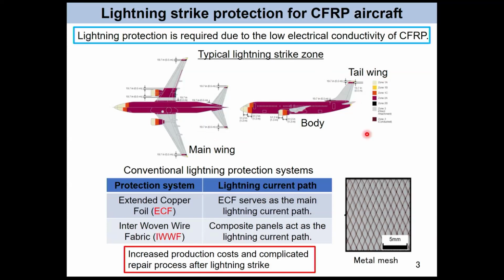The current lightning protection system, the representative one, is expanded copper foil. The copper foil is a metal mesh like this, and the metal mesh is attached on all the CFRP surfaces. When lightning strikes the surface, this mesh acts as a current path, Joule heating is suppressed, and severe damage should be avoided. But this metal mesh is handled manually, which increases production cost and complicates the repair process after a lightning strike.